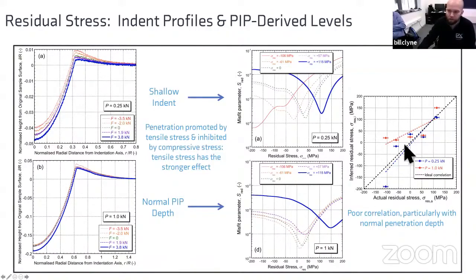And this is summarized in this plot here, which shows the inferred residual stress against the actual residual stress. And we can see that at low penetrations, we're getting a reasonable agreement in terms of at least the correlation, but there's a lot of scatter around that. And then at the higher depth, we're getting very poor sensitivity to the residual stress.